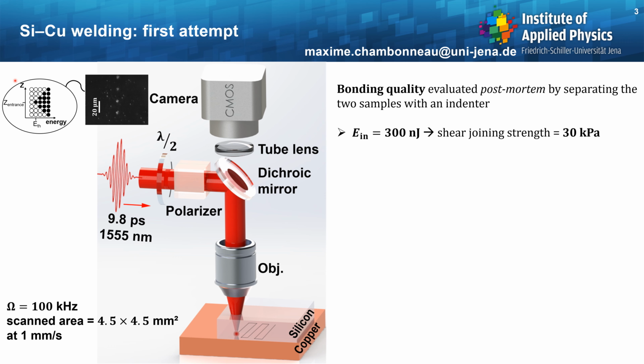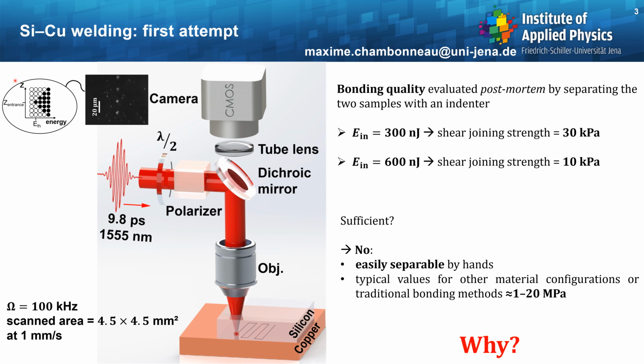Let us set the input pulse energy at 300 nanojoules, and we can measure a shear joining strength of 30 kilopascal. All right. But then what if we double the energy? So for an input pulse energy of 600 nanojoules, the shear joining strength is 10 kilopascals. All right, so the main question here is, is it sufficient? I mean, can we say that silicon is welded, is joined on copper? Sadly, the answer is no. And actually, in this case, the samples are easily separable by hands. And typical values for other material configurations or traditional bonding methods are on the order of 1 to 20 megapascal. So the main question here is why?